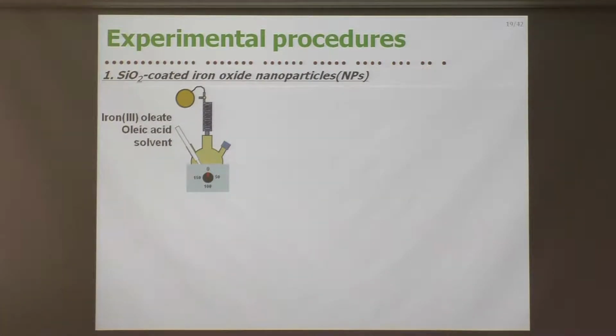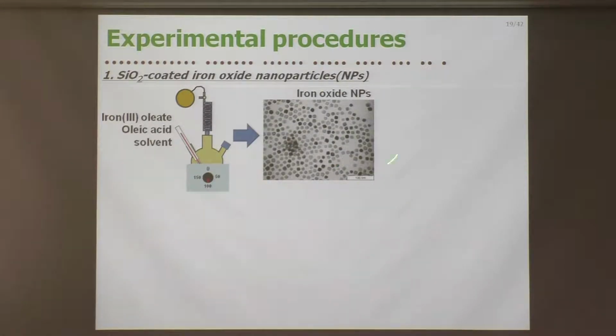The first process is the preparation of the iron oxide nanoparticles coated with SiO2. At first, we prepared the iron oxide nanoparticles using iron(III) oleate as a source of iron, oleic acid as a surfactant, and some solvent. We used tri-n-octylamine as the solvent, with a boiling point of about 350 degrees Celsius. Here shows the typical TEM image of the iron oxide nanoparticles we prepared.